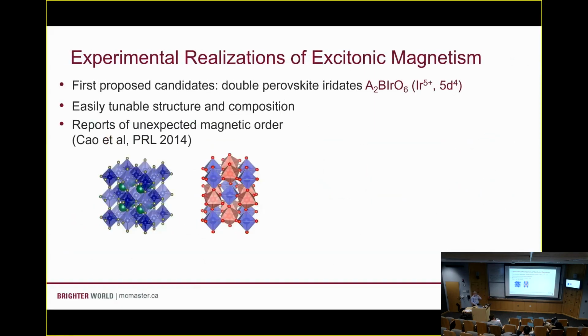There were a number of systems that were proposed as possible candidates for this kind of magnetism. The first materials that people went to, again, where you look for weird spin-orbit driven things, is where the spin-orbit coupling is strongest. So the first stop was iridates. Now again, instead of going to iridium 4+, which is 5d5, we're looking at iridium 5+, which is 5d4. And this double perovskite crystal structure, for those of you who aren't familiar with these materials, the real advantage of this structure is that it's really easily tunable.